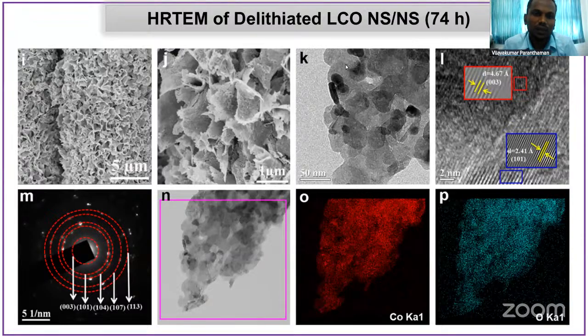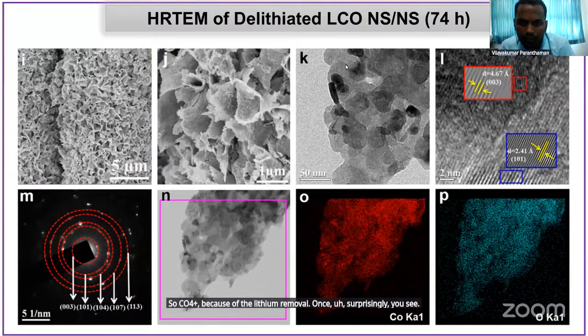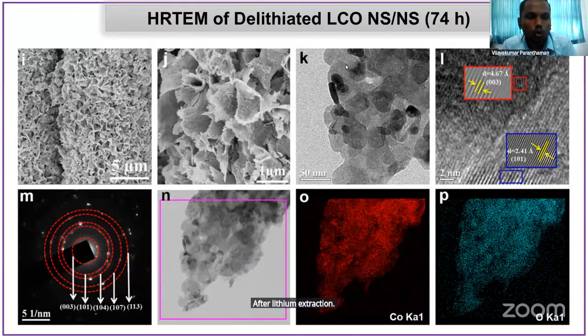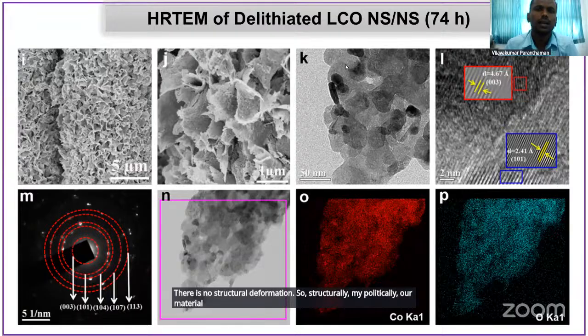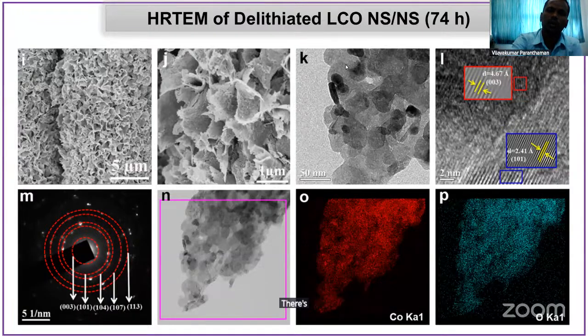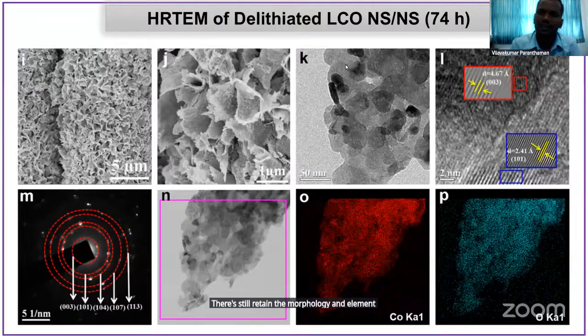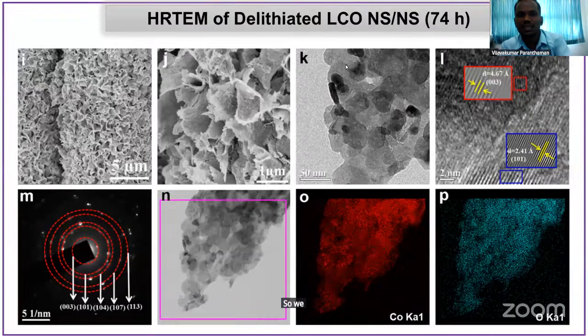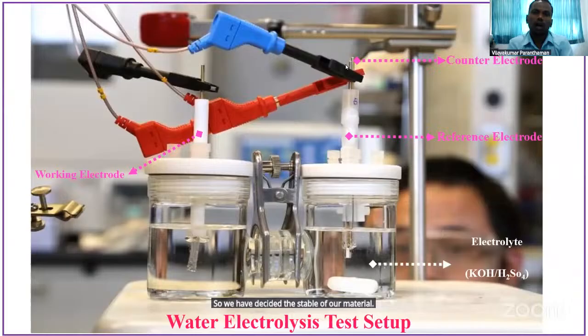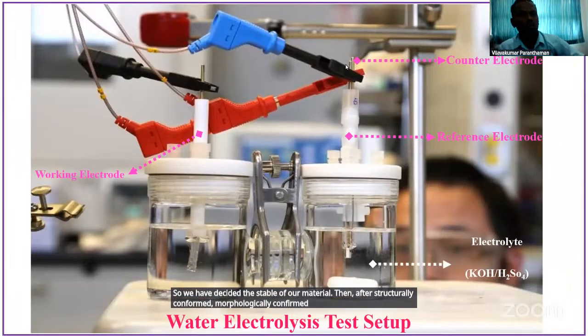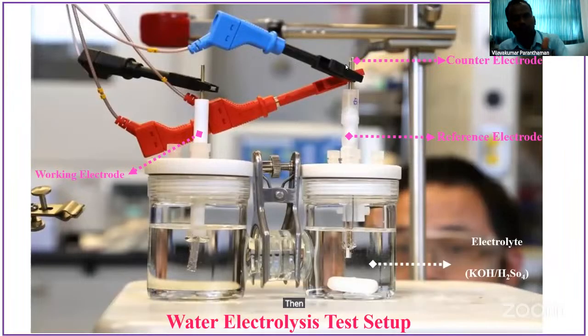Surprisingly, you see after lithium extraction, even in the 74 hour samples, there is no structural deformation. So structurally and morphologically, our material is a stable material. It still retains the morphology, and the elemental composition is all the same. So we have decided our material is stable. Then after it is structurally confirmed and morphologically confirmed, you have achieved what you want. Then the next step, we are moving to the application side.